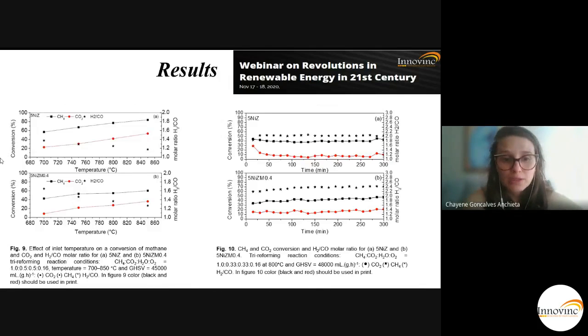Now looking at the reaction results, here we can see that we have a temperature effect. As we have exothermic and endothermic reactions in the system, we know that by increasing the temperature, we improve the methane and the CO2 conversion. Also, we saw that we have a reduction in the molar ratio considering both systems, with and without ionic liquid in the support, when we change the temperature of the reactions. Here we use stoichiometric conditions of the tri-reforming reactions.